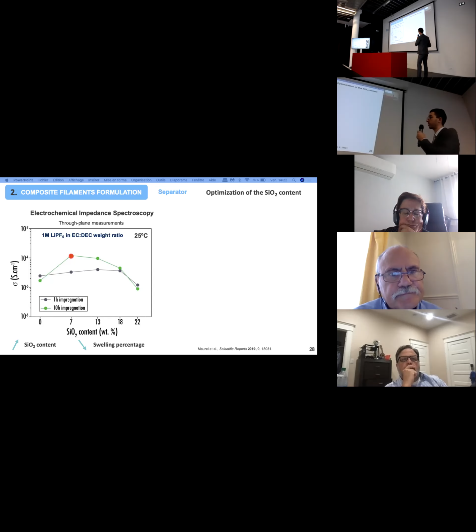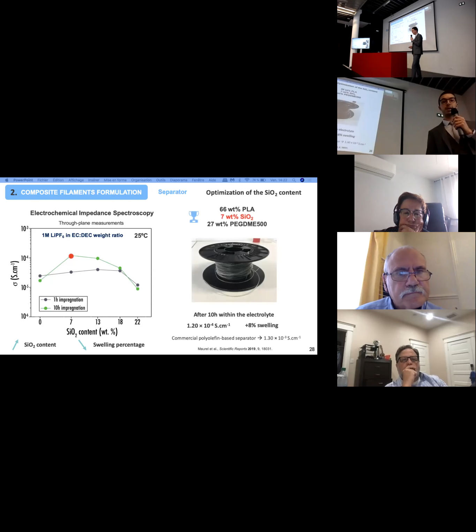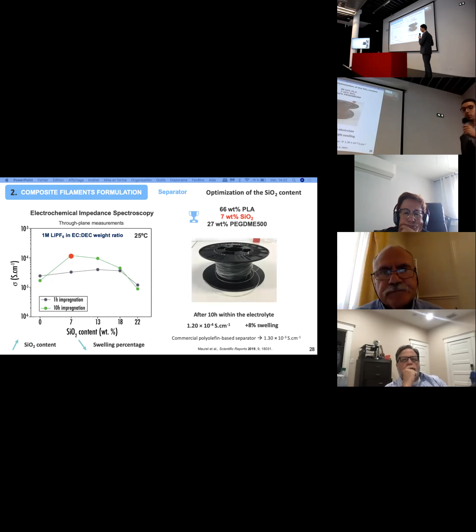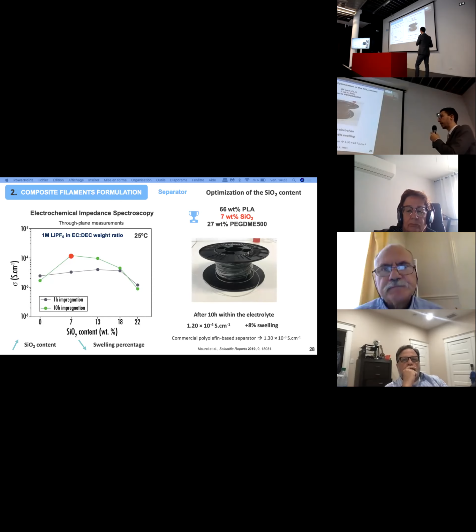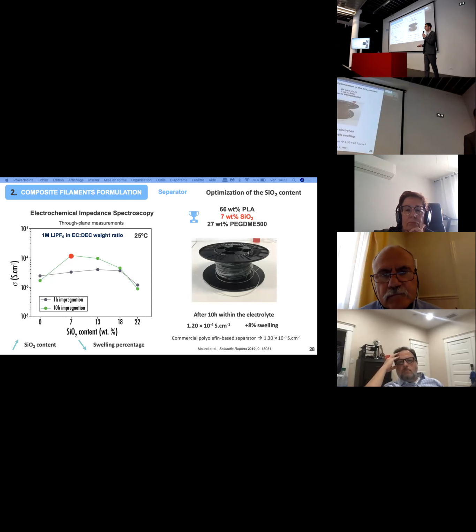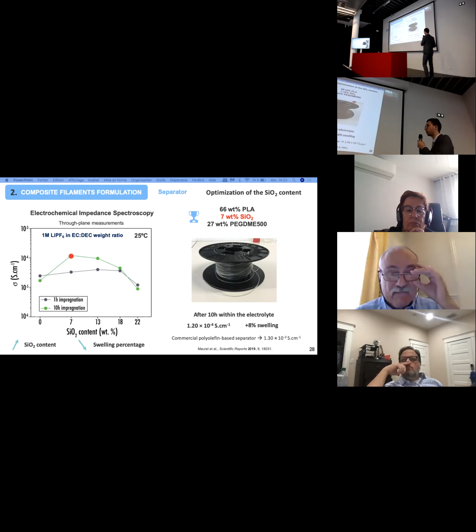Here you can see that there is a red dot appearing in this graph, and this red dot corresponds, after 10 hours of impregnation within the liquid electrolyte, to the optimized value. This optimized value corresponds to 7% silica content. So we then produced filaments with this particular composition. After 10 hours within the electrolyte, we obtain an ionic conductivity value of about 1.2 × 10^-4 Siemens per centimeter, which is quite promising, but still far from a porous polyolefin-based separator, which displays values 10 times higher.